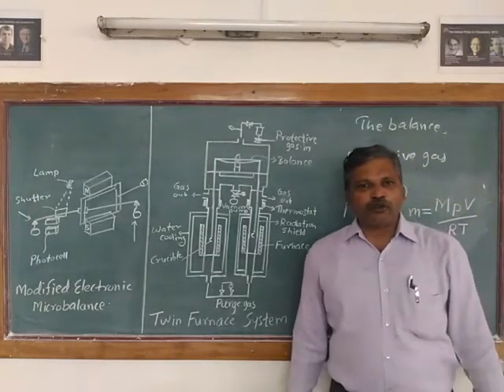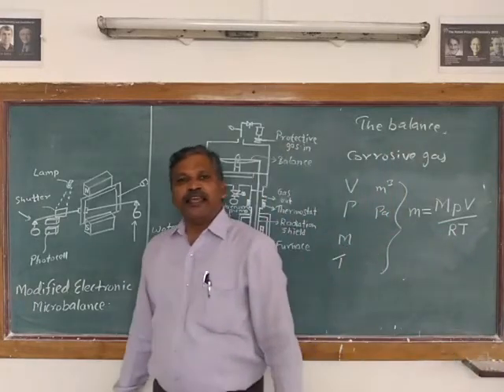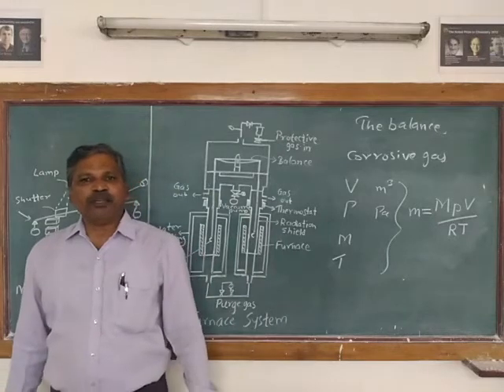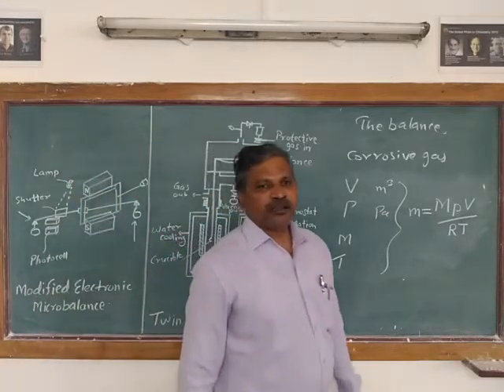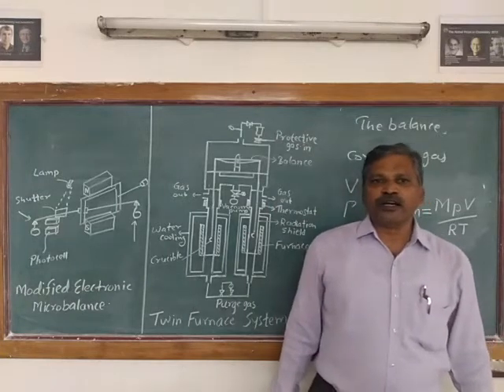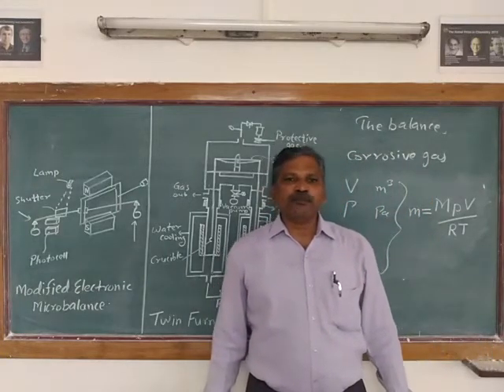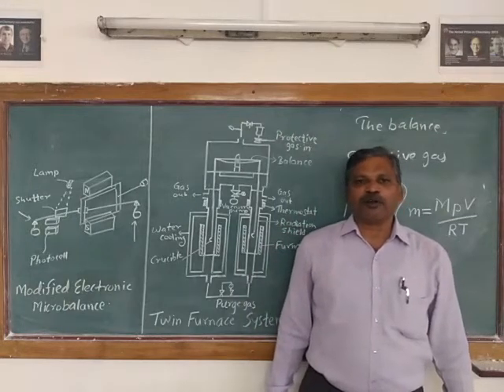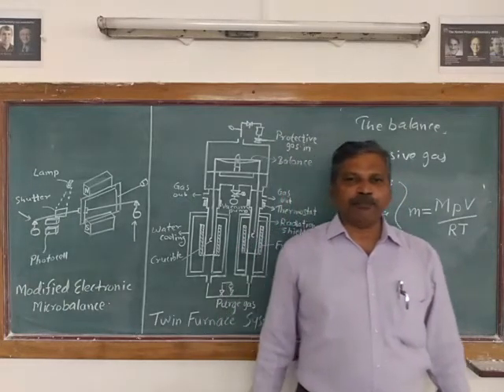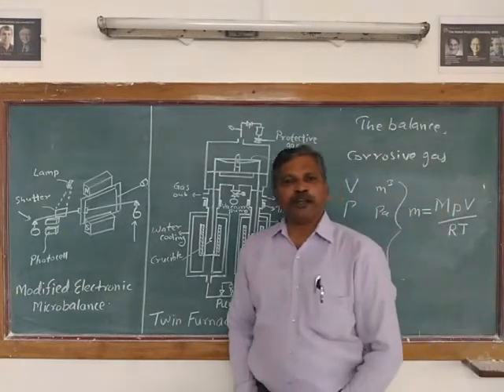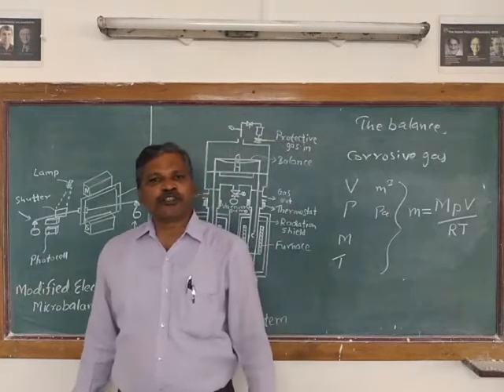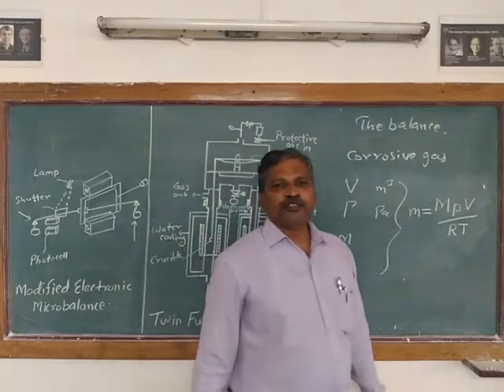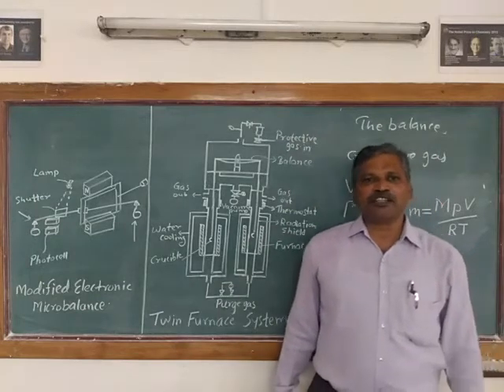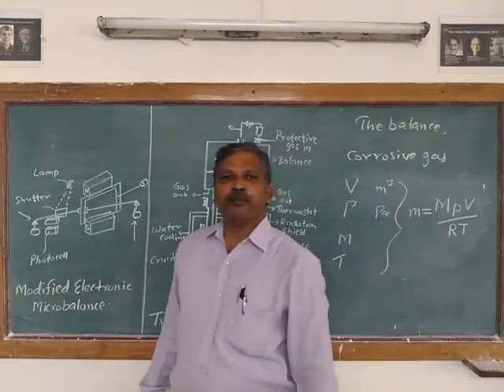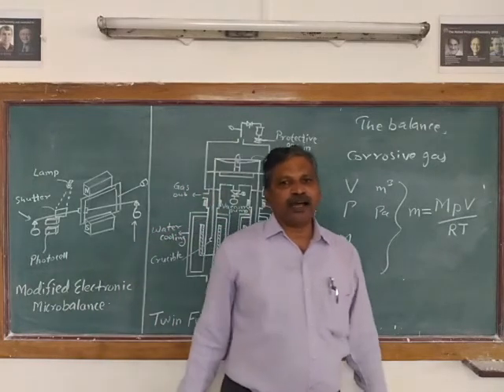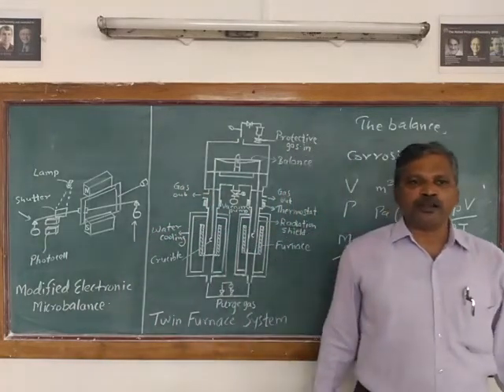There are several ways to compensate for this effect. The gain in the mass of the sample can be avoided in different ways. Firstly, run a blank buoyancy curve with an inert sample of similar volume and subtract that curve from the experimental curve for our sample. You will have to obtain the reference curve by using the blank buoyancy curve, or by using a reference material. Whatever curve you get will be called the blank buoyancy curve. That curve has to be subtracted from the experimental curve.